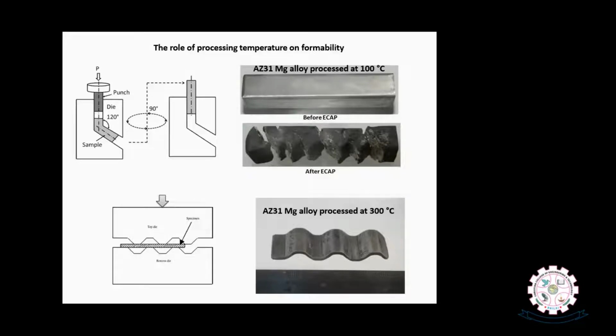This is the process. For example, here this schematic diagram shows you ECAP process, and the typical photographs demonstrate to us the lack of deformation at lower temperatures for AZ31 magnesium alloy. You can see how the material has fractured during the process. Whereas the same material, AZ31 magnesium alloy, in the form of sheet, you can see when it is deformed between two corrugated dies in groove pressing at 300 degrees centigrade, the same material has been successfully deformed because of the activation of the other slip systems of prismatic and pyramidal planes.